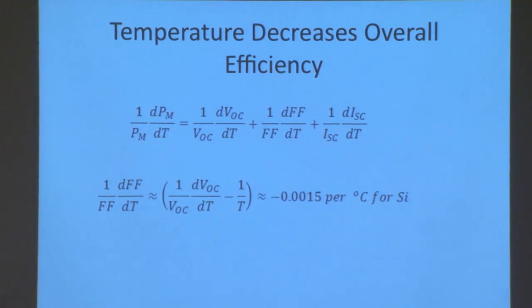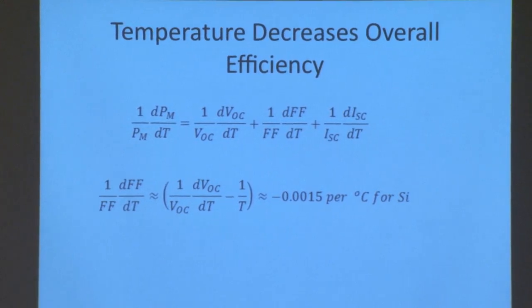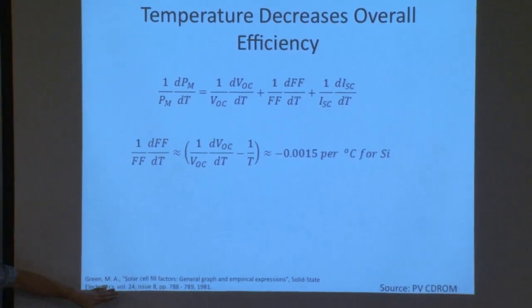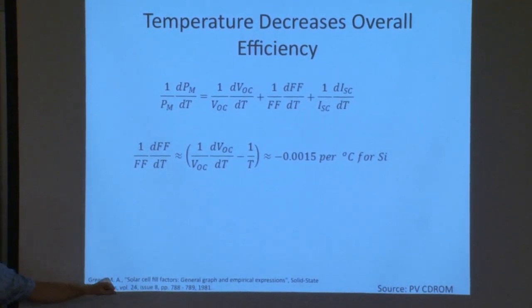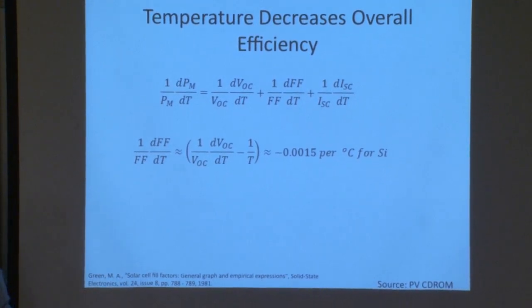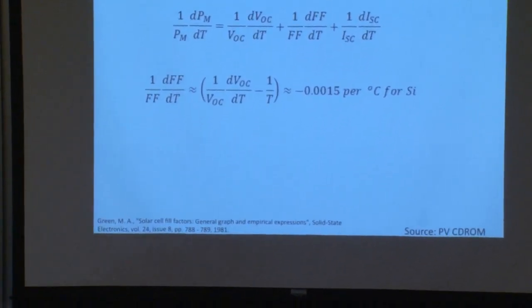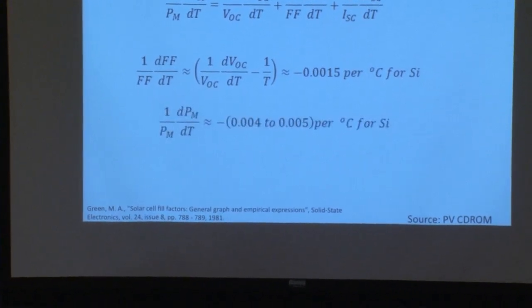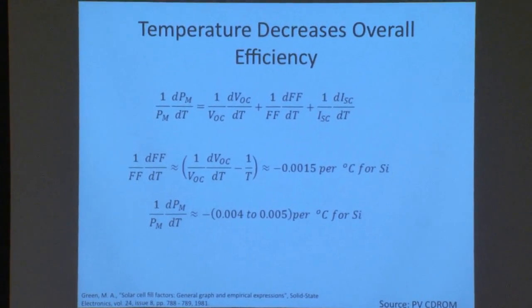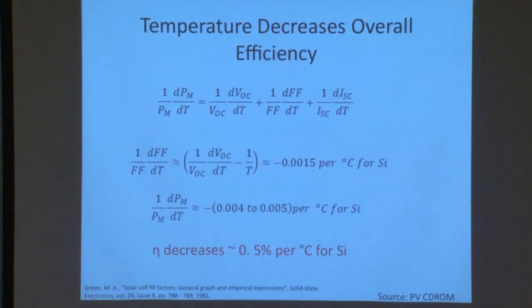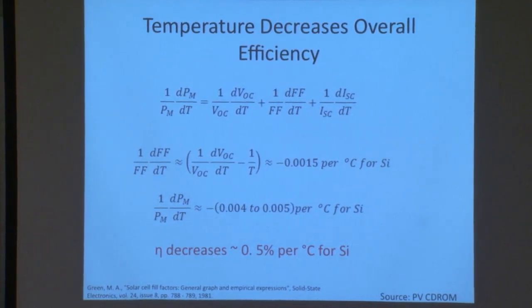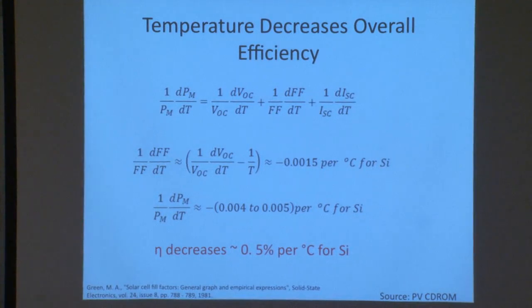This is all in Martin Green's paper down here, and also on PV/CD-ROM. If you guys are interested in that, Martin Green's tabulated a lot of this, making these general expressions and also fitting it to experimental data to get that information. And then it ends up being not a negligible percent, but about 0.5% per degree Celsius for silicon. So if you go up by 40 degrees, you can see that temperature is a non-negligible effect in terms of performance.